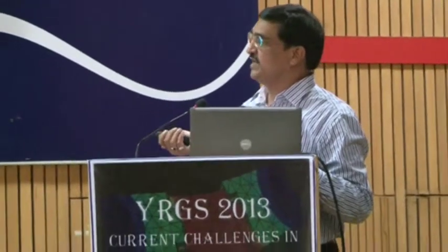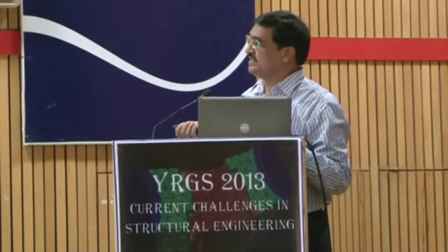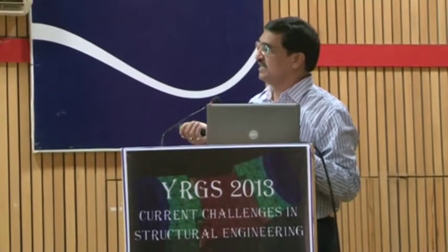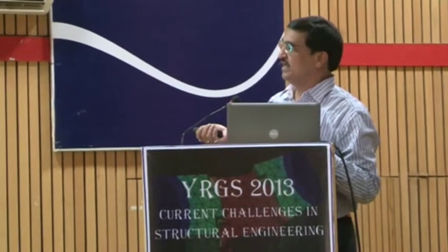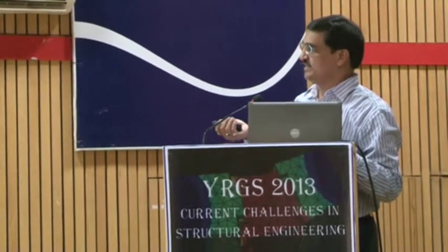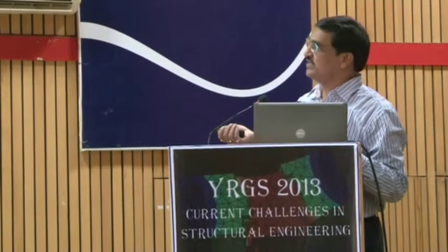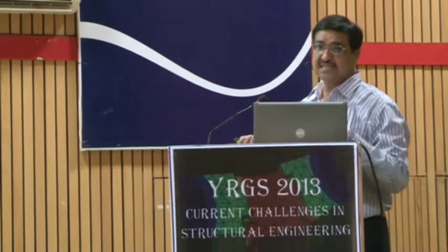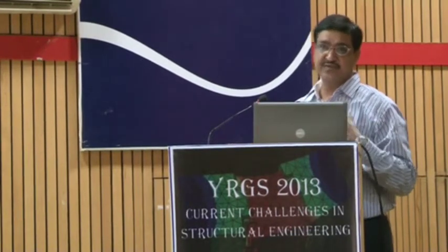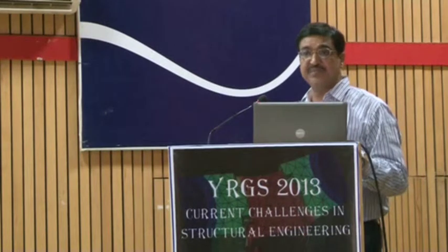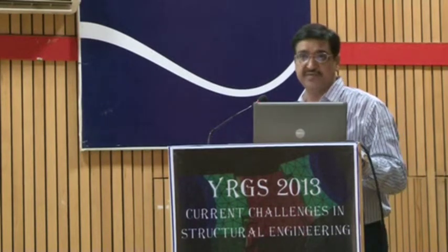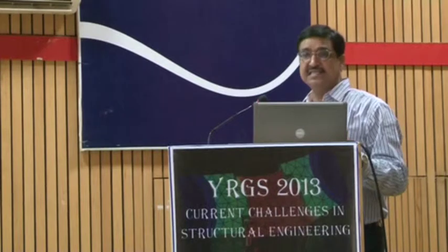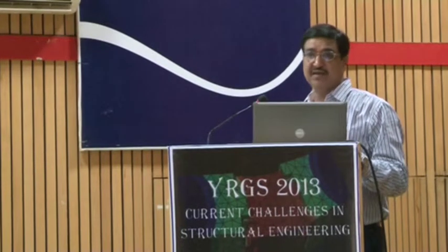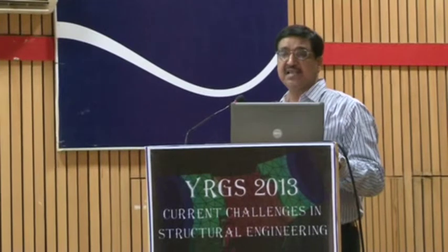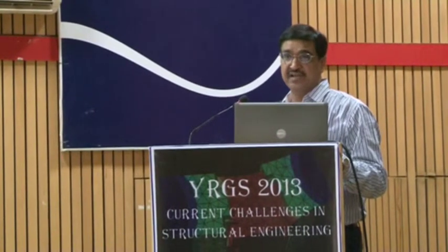See that in normal FRC concrete it just goes to the peak and then the strain softening branch starts here. But in the case of typical ECC material, we have a strain hardening branch starting after the first cracking and peak, and then the strain softening branch starts from the peak. This strain hardening branch is not there in a typical FRC system, and that's the advantage of ECC material, which can be applied for external strengthening, because you are not looking at the whole structure, but you are looking at ECC as a precast element in layers or at plastic hinge locations, and then we can get sufficient strength as well as ductility.